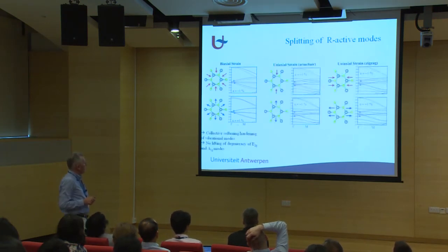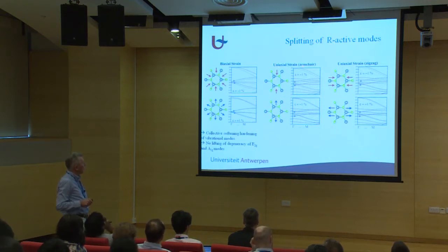Then if we use uniaxial strain, in the armchair or the zigzag direction, you see that indeed the degeneracy of the phonon energies is lifted, and you only need about 1% of strain.